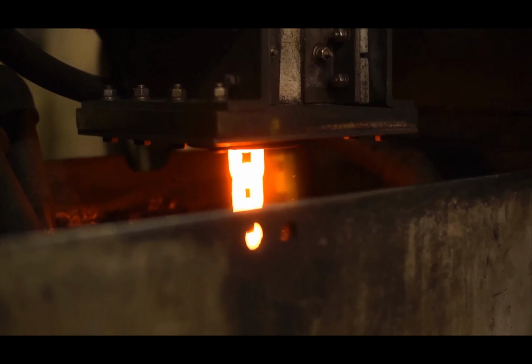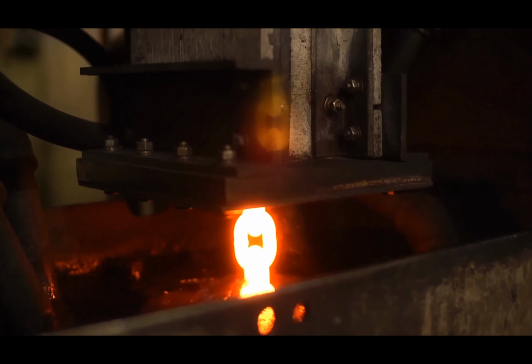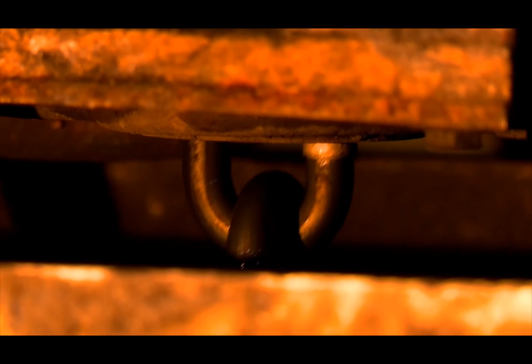All transport and alloy chain is sent through our continuous induction heating, quenching, and tempering line. Chain is heated to over 1600 degrees Fahrenheit, water quenched, and then tempered at over 400 degrees Fahrenheit. This all occurs in less than 20 seconds. From here, the chain will then be proof tested using our automated system. Now, let's take an in-depth look at one of our proof testers.